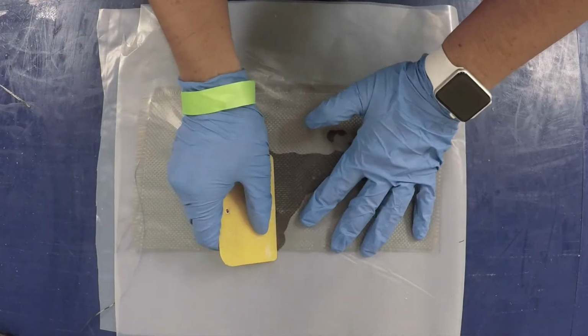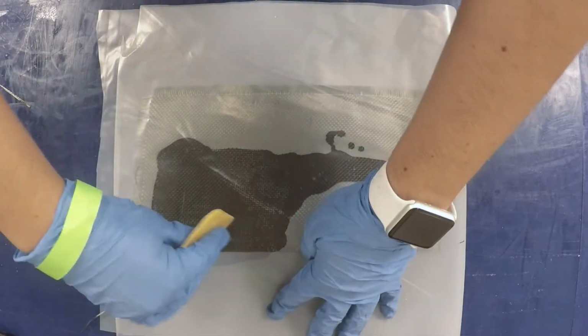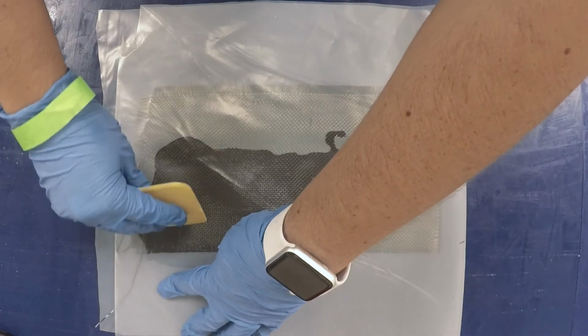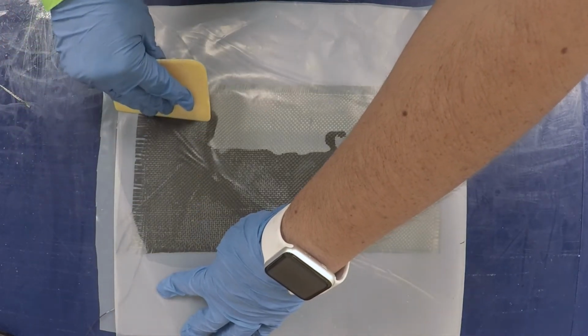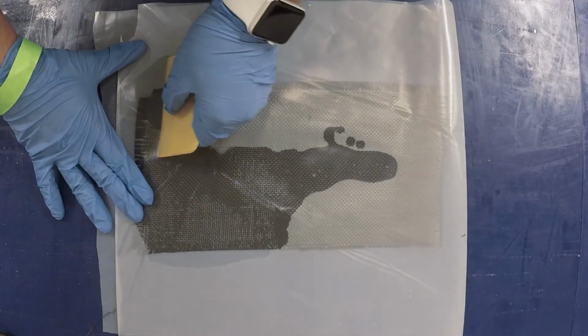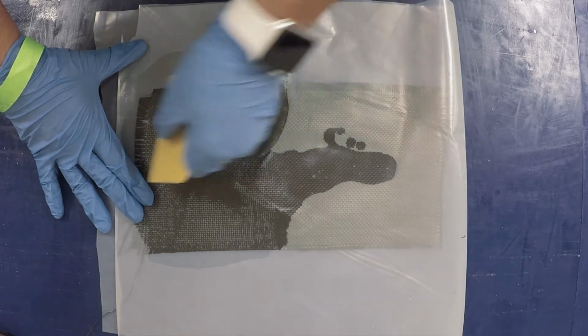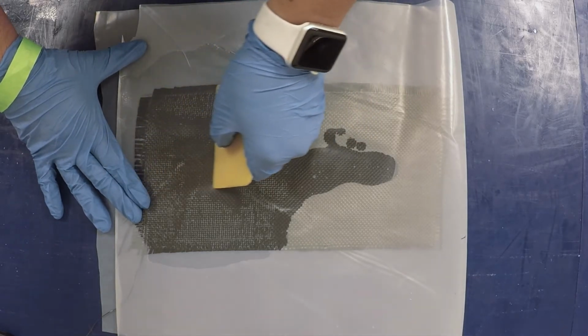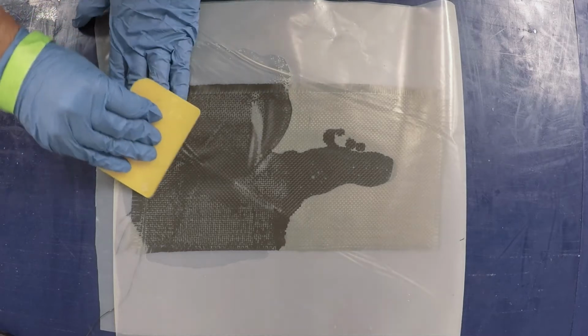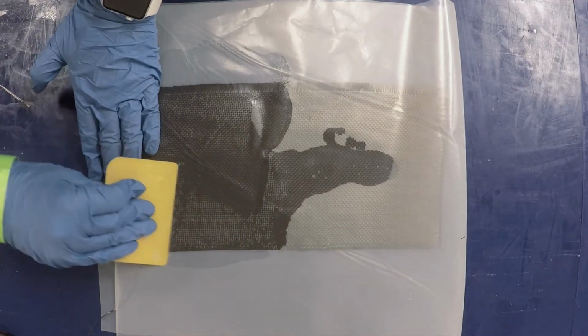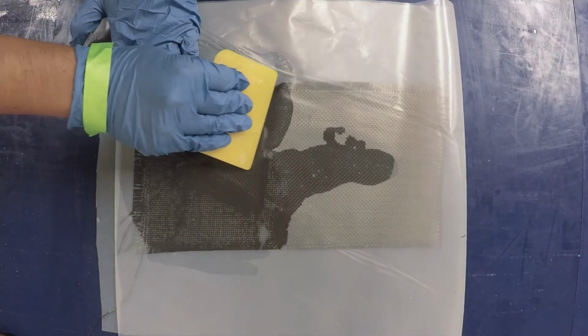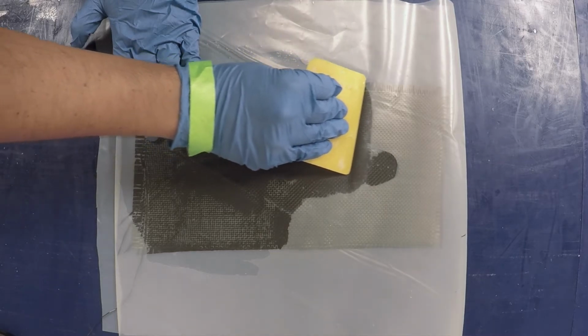As you are spreading the epoxy into the layer of fabric, be sure to pay close attention and not miss any dry spots or produce any overly saturated spots. The direction of where and how you push isn't important as long as you spread the epoxy evenly. Be careful not to press too hard as to distort the fibers.